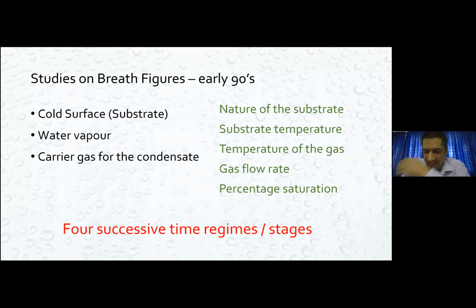The flow rate is required for pattern formation. And then the percentage saturation: if it is highly saturated, a larger number of droplets are formed at the initial stages, and so on. So they concluded that there are 4 successive regimes or stages in any droplet condensation onto the surface.